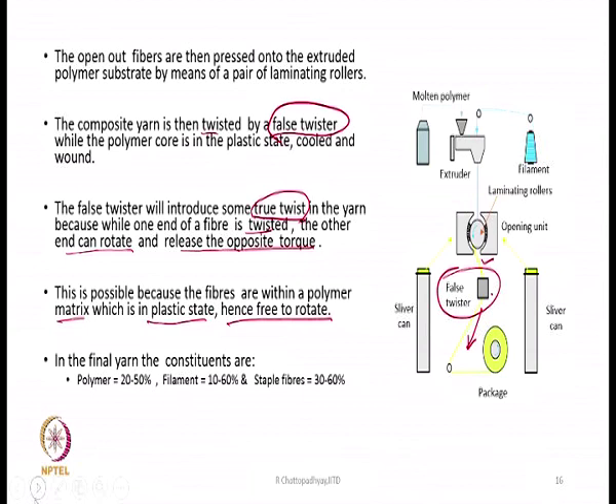So, typically the final yarn constituents are: polymer can vary in percentage, let us say 20 to 50%, and filament percentage could be 10 to 60%. Remember, the filament is going to give strength to the entire yarn. If the filament is strong, the yarn is going to be strong. Staple fibers can vary between 30 to 60%. So, these are the ranges in which the polymer, filament, and staple fibers can be varied, and we will be able to produce a yarn having filament, polymer, and staple fibers. So, several fibers will be seen on the surface.